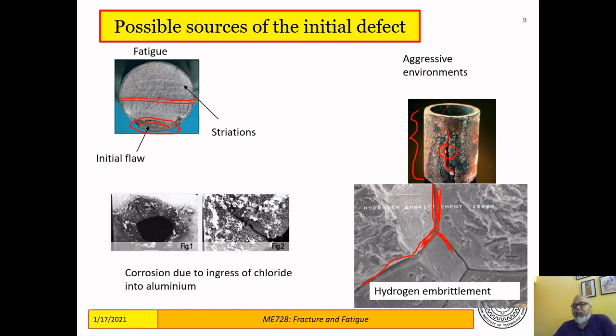they have cracked, and they have actually cracked because of the hydrocarbon that was flowing through the pipe, that leads to infusion of hydrogen into the steel of the pipe material, and this hydrogen reacts with certain elements in the steel and leads to what is known as hydrogen embrittlement, which is basically a weakening of the grain boundaries, and that leads to small defects which grow and finally lead to a crack of the sort.